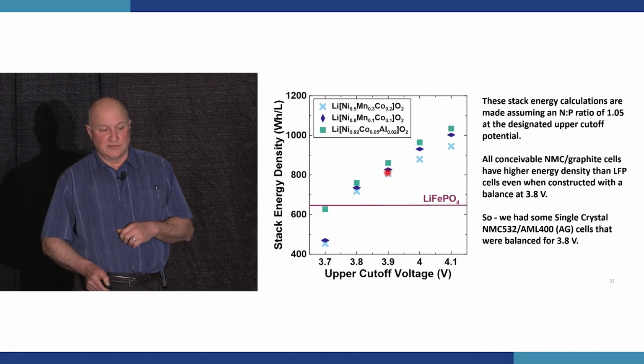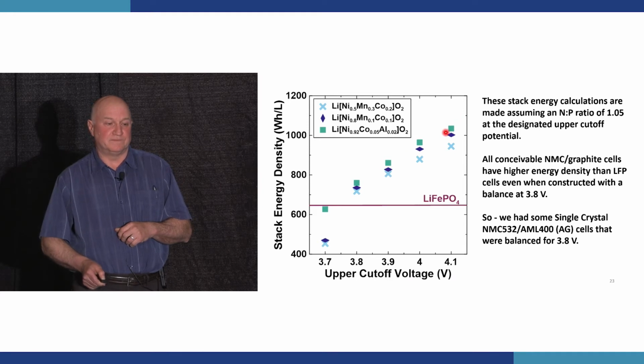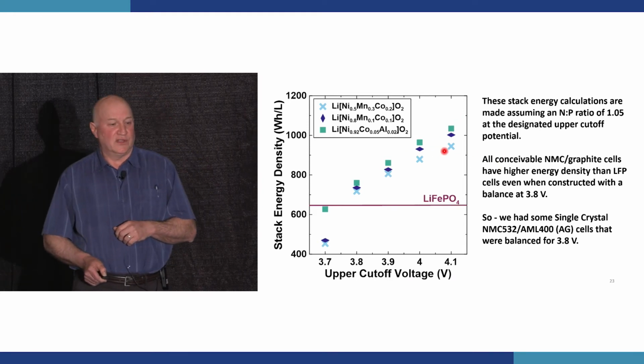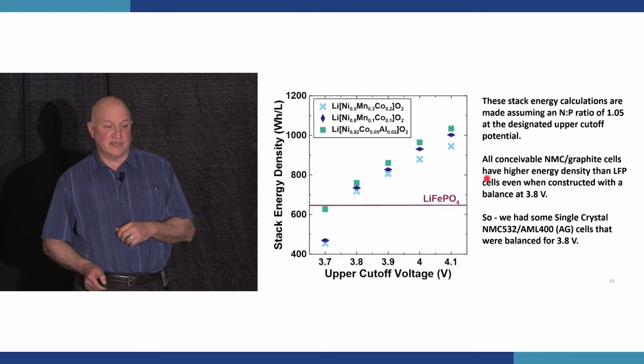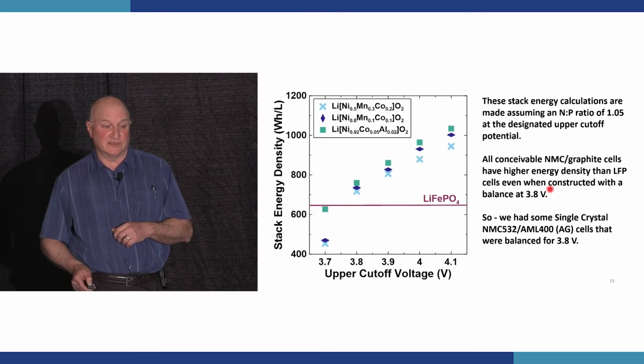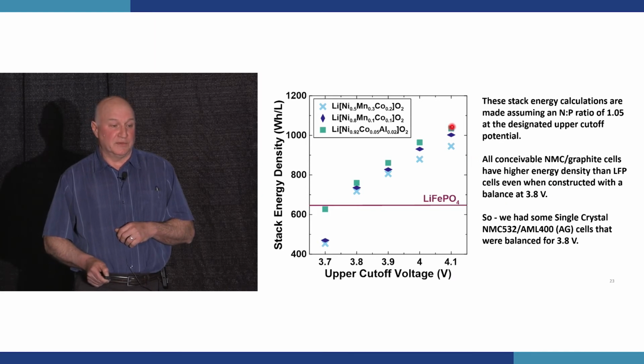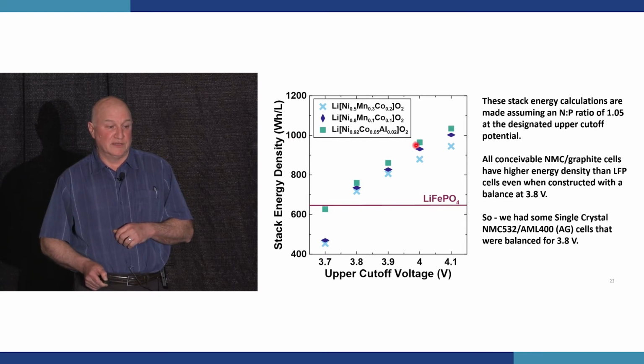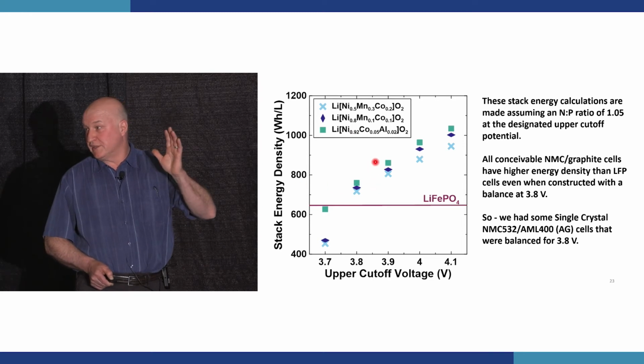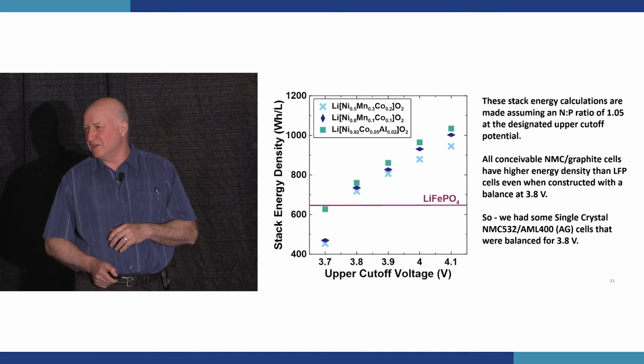If you go to 3.9, it's higher, and so on. So the point here is all conceivable NMC graphite cells have a higher energy density than LFP, even when they're constructed with a balance of 3.8 volts. And if you think about it, at 4.1 volts, you have about 1,000 watt-hours per liter. If you go down to 3.8 volts, it's over 700. You give away about 27% in energy density. But what happens if you get a factor of 10 in lifetime? Maybe that's worth having.